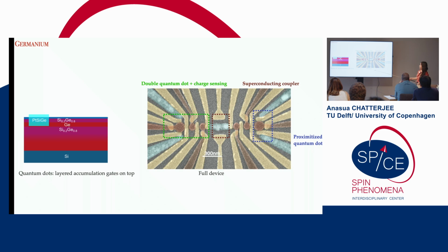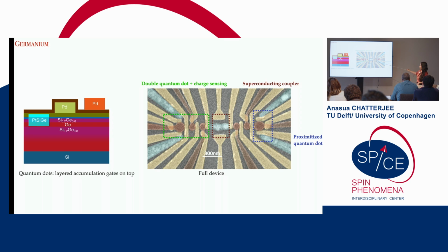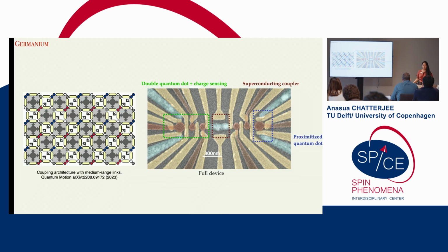The way we do it is, first we anneal in these blue regions, the platinum germanosilicide, and they superconduct. Then we add oxide. We put the first layer of palladium gates, another layer of oxide, and then the barrier gates on top of that. So that seems to work pretty well.